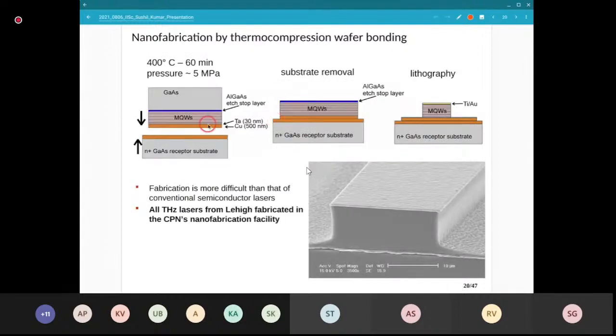This is what I mentioned to you about fabrication. This was the MBE wafer that we received from our collaborator. They grow these layers and send us this wafer, then we deposit metal, take a dummy wafer and deposit metal on that, and we thermocompression bond it by compressing it at a hot temperature.